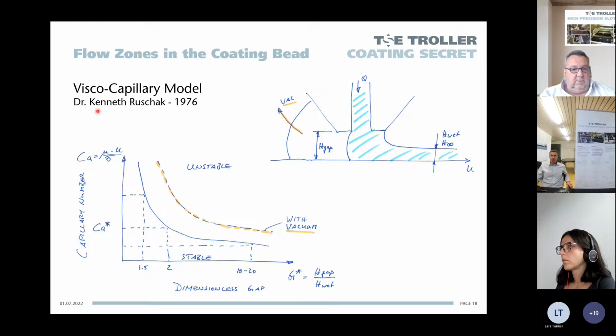And Dr. Ruschak has found the so-called viscocapillary model, which helps to explain what's going on in the flow field. This curve here shows the transition between the unstable condition and the stable condition. In the diagram, we see here the dimensionless gap, or the gap ratio between the coating gap and the wet thickness. So the coating gap here and the wet thickness. And here you see the capillary number.